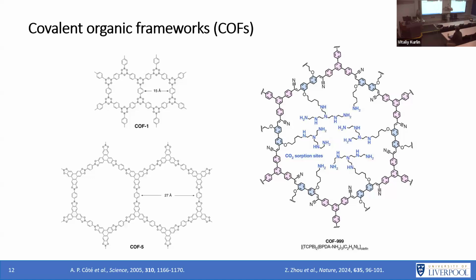And this field has also gone from strength to strength. There's many people working in the field of COFs as well. And just last year there was COF-999 published. And this is an olefin functionalized COF, and it's actually been functionalized with amines. And this just means that it's made it really good for absorbing carbon dioxide. So again, it's just showing that you can do similar kinds of chemistry with related frameworks to metal organic frameworks, and you can functionalize them in lots of different ways, in this case for carbon dioxide capture.